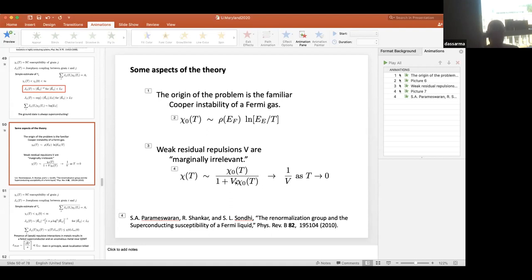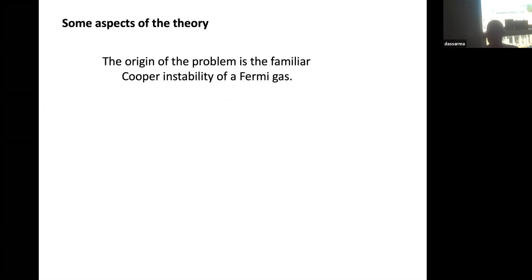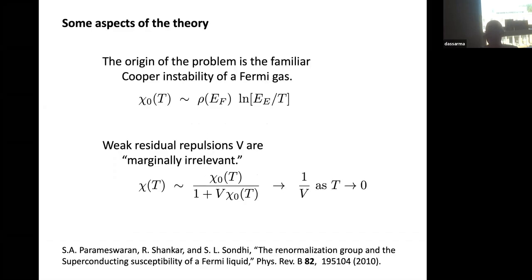Okay. But I got something from you, which is, I think, quite interesting. That you are actually arguing that even if the system goes ferromagnet, that may help superconductivity. It's not necessarily that it destroys it. No. If it goes ferromagnetic, that's going to kill it. So if it goes ferromagnetic, for sure, that will mean that in the singlet channels that we're looking at, the superconducting susceptibility is finite. But even sufficiently large ferromagnetic fluctuations can do that.